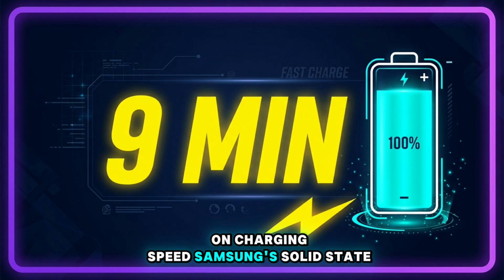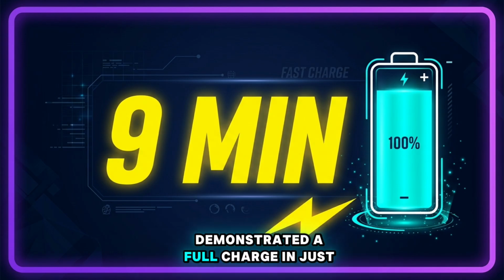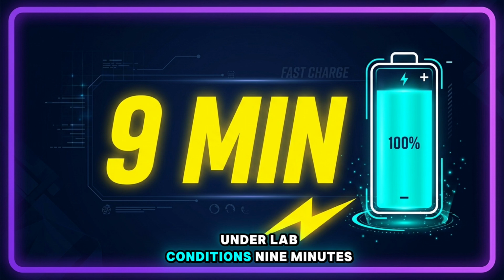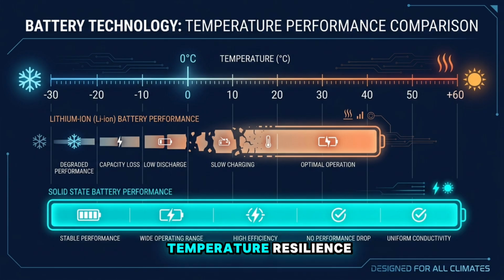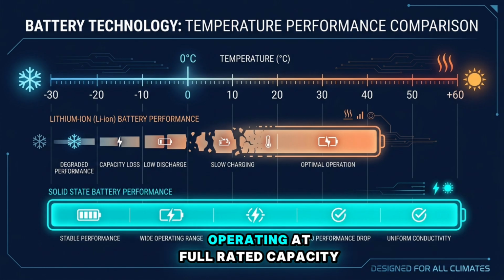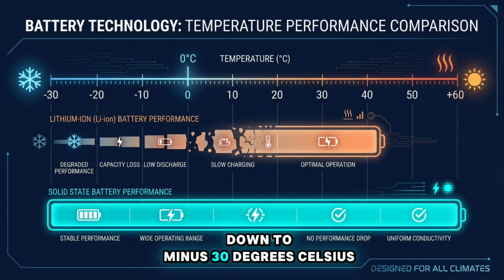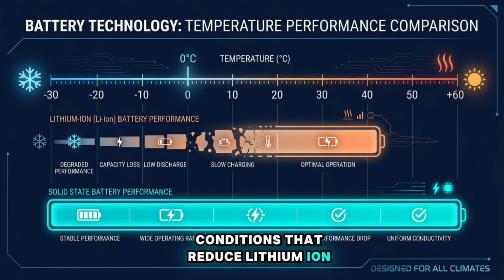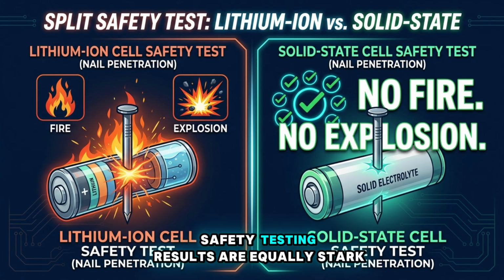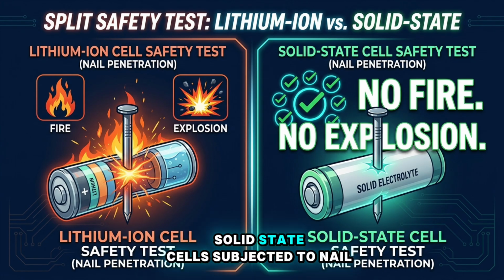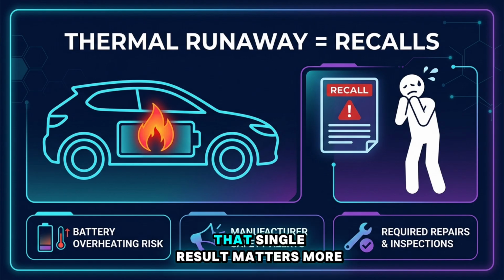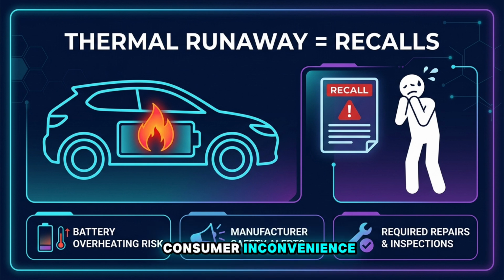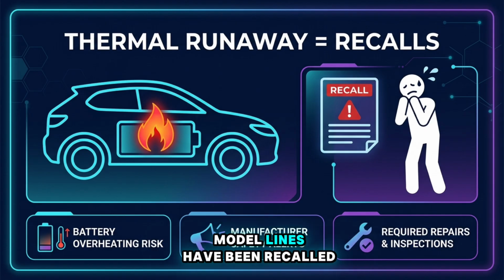On charging speed, Samsung's solid-state research division demonstrated a full charge in just 9 minutes under lab conditions. 9 minutes for a full battery. Temperature resilience testing shows solid-state cells operating at full rated capacity down to -30 degrees Celsius, conditions that reduce lithium-ion output by up to 50%. Safety testing results are equally stark. Solid-state cells subjected to nail penetration tests, the standard method for triggering thermal runaway, showed no fire, no explosion, no rupture. That single result matters more than almost any other metric, because thermal runaway isn't just a consumer inconvenience, it's the reason entire EV model lines have been recalled.